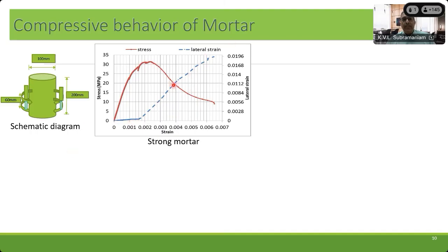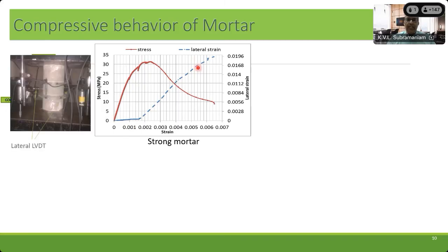So this blue line here shows the lateral strain, which is basically the expansion that is produced in the mortar as I'm applying the compressive stress. So we are applying the compressive stress on the cylinder and we are measuring how much it is expanding. What you notice here is up to the peak, there is a little expansion. But you see what happens after the peak load. After the peak, there is a tremendous amount of expansion that is taking place. So this material expands a lot. It actually dilates a lot close to failure.